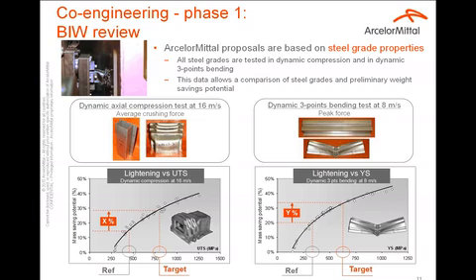In the phase 1 of the co-engineering approach, ArcelorMittal proposals are based on steel grade properties. All steel grades are tested in dynamic compression and in dynamic three-point bending tests. As you can see on this animation on the left-hand side of the slide, here is the crash test we perform on hat structure in our research center equipment. This data allows a comparison of steel grades and preliminary weight saving potential, as described on the graphs for compression and for anti-intrusion part on the right-hand side.